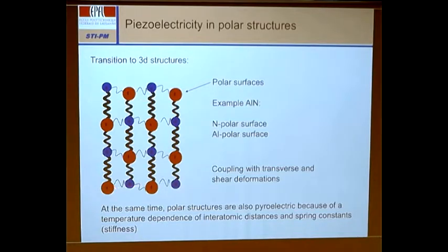And you see that the two ends must be different. So crystals then have some kind of positive or negative faces. For instance, in aluminum nitride, one speaks about the N-polar surface or the aluminium polar surface. So they are different, and not only in the dipole sense. You see it's a dipolar surface, but also chemically they are different. So in such structures you always find agents that attack one polarity but not the other. It's very interesting. This means that, for instance, ferroelectric materials can also be used in electrochemical reactions in an interesting way. It has also been shown.